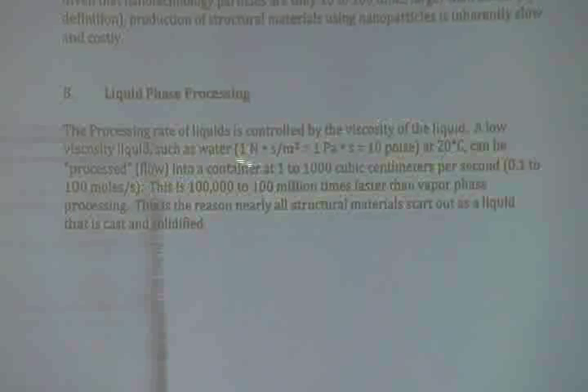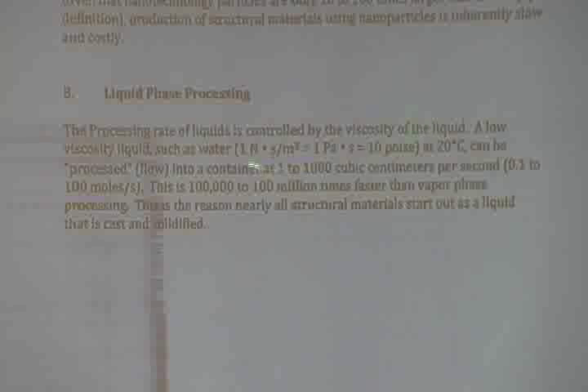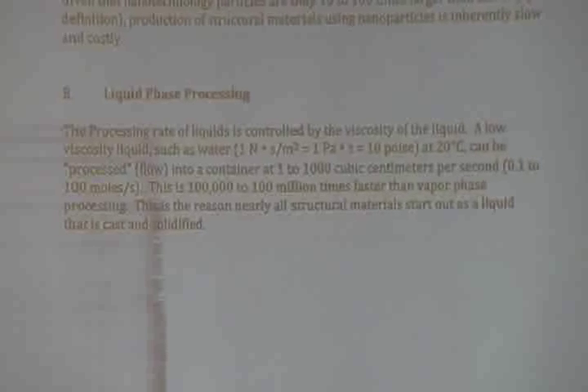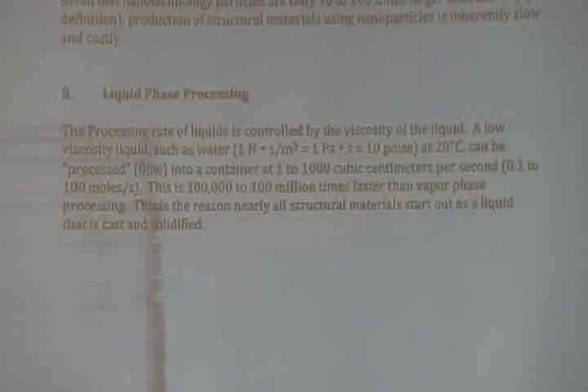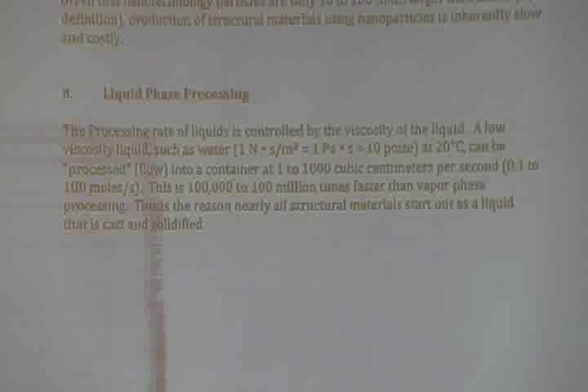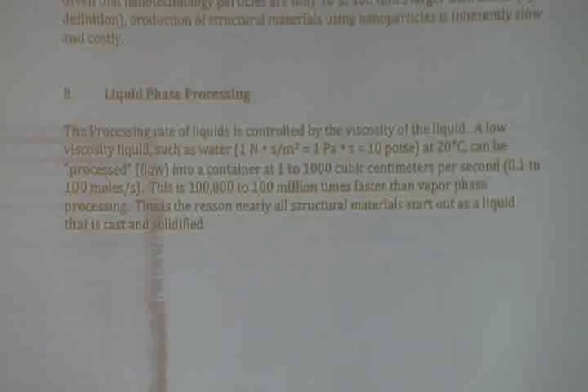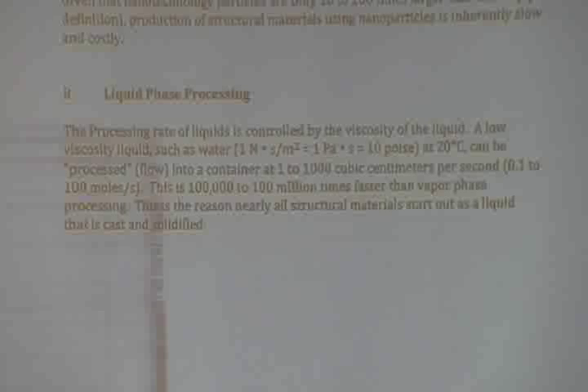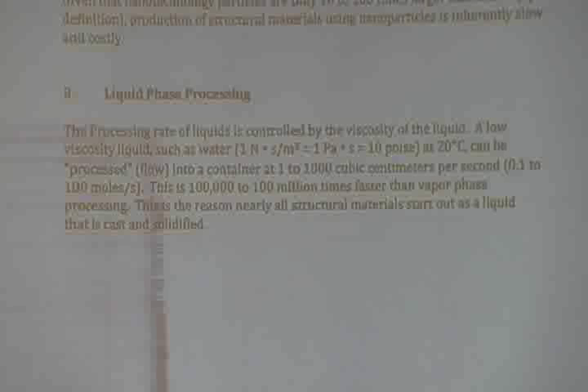And you can pour it into a mold. So you flow it into a mold. Viscosity is the parameter of choice. And you're going to find that liquid phase processing is somewhere between 100,000 and 100 million times more efficient than vapor phase processing. Because structural materials are used in very large volumes, as compared to often small volumes for functional materials, we start with a liquid and cast. Virtually every structural material starts out as a casting. That's not always true of some of the ceramics, but all the metals start out as a liquid. They don't go through the vapor phase route,